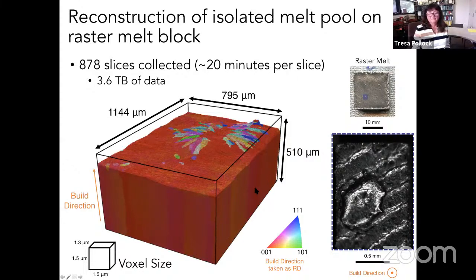And for applications in aerospace, columnar structures are often desirable because grain boundaries are places where damage can accumulate in the structure. And so we have the strongly columnar structure with this melt pool at the very top of the structure. And what you can see is that there are some grains that have nucleated on the surface, and there are some grains that have actually melted epitaxially and grown up through the melt pool.